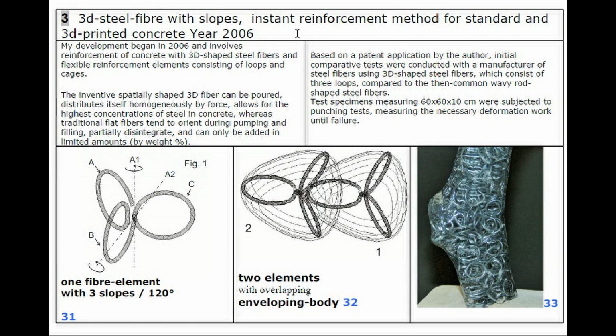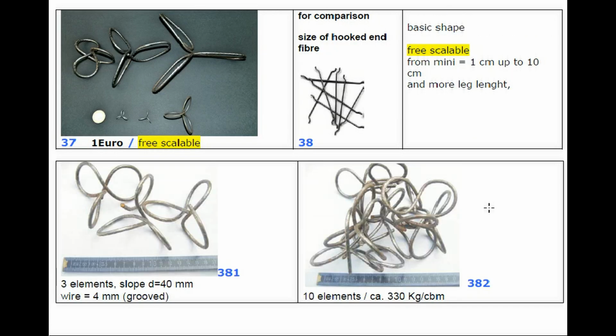I started in 2006 with that fiber element with 3 slopes in 120 degrees. Here you see 2 elements with overlapping, enveloping bodies. You can see these elements can be filled into a form and are homogeneously dispersed, and so they are very dense. This fiber idea is freely scalable from 1 centimeter diameter up to 10 or 15.